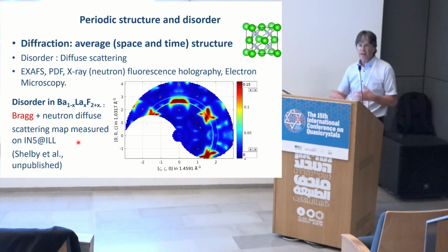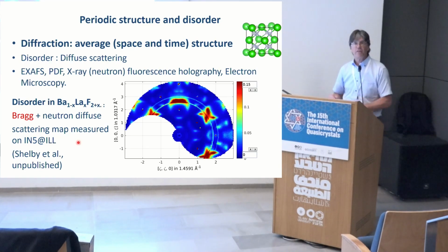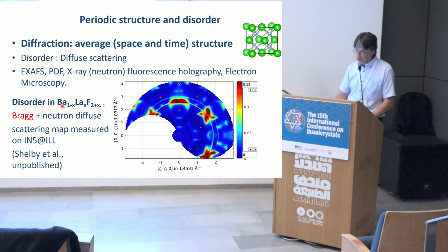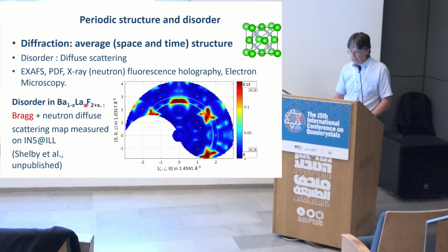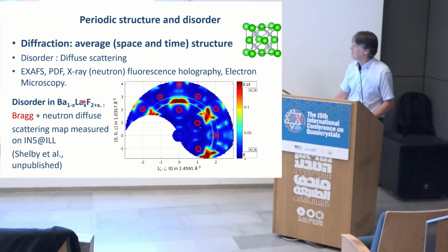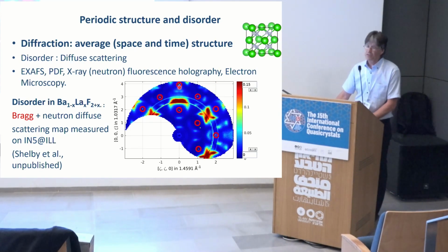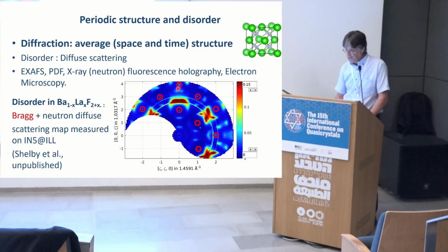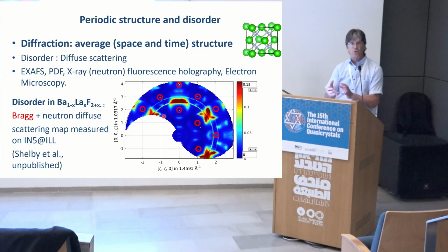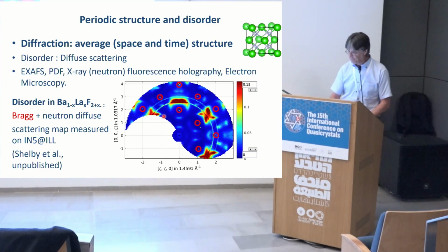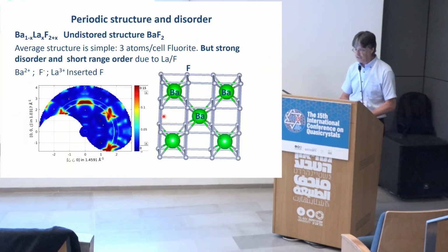So besides the Bragg peaks, we also have a signature of the disorder, and it's illustrated here in this barium lanthanum fluoride. It's barium difluoride, where we have substituted barium by lanthanum. So we have Bragg peaks. The Bragg peaks in this figure are just these tiny dots. You don't see them because they are very sharp. And all the rest is what we call diffuse scattering, and is related to the disorder which is inside the structure. And the disorder is shown in the next two slides.